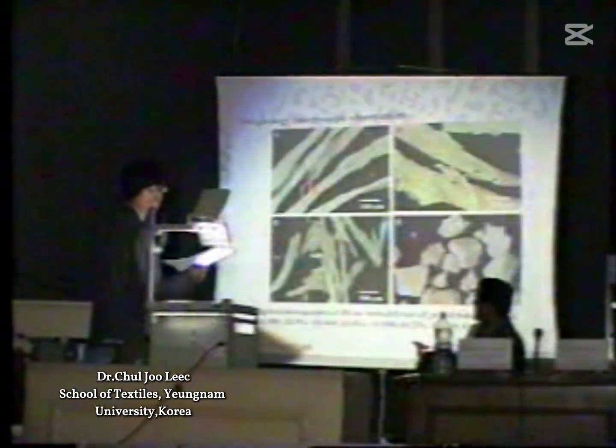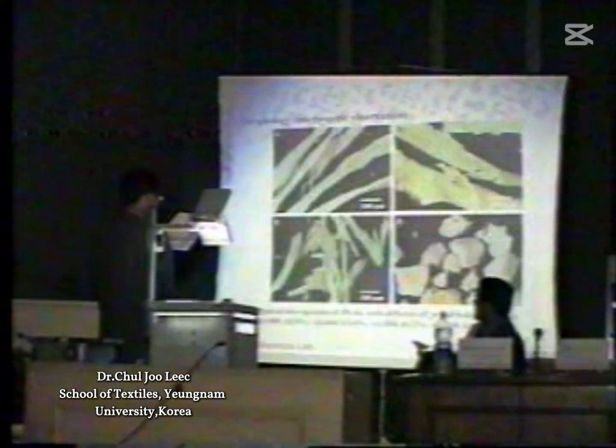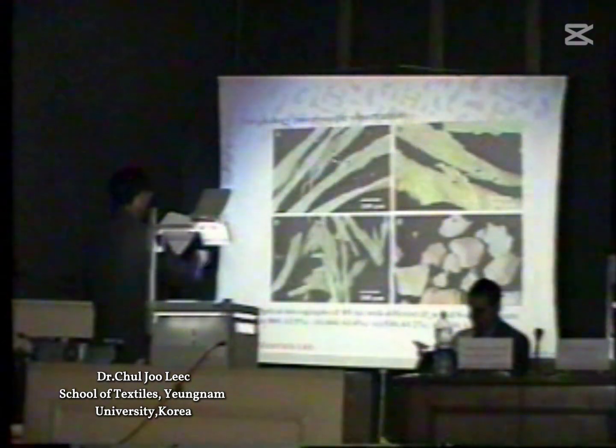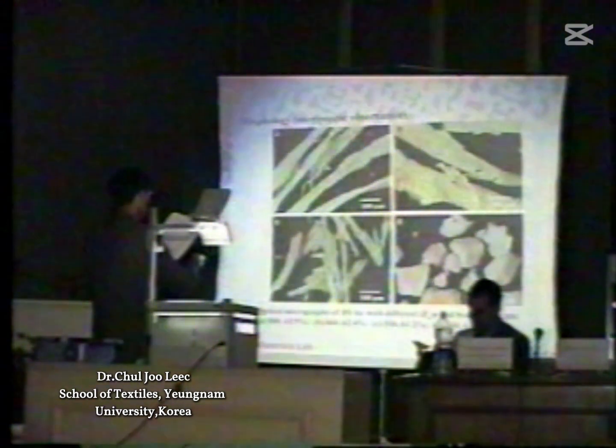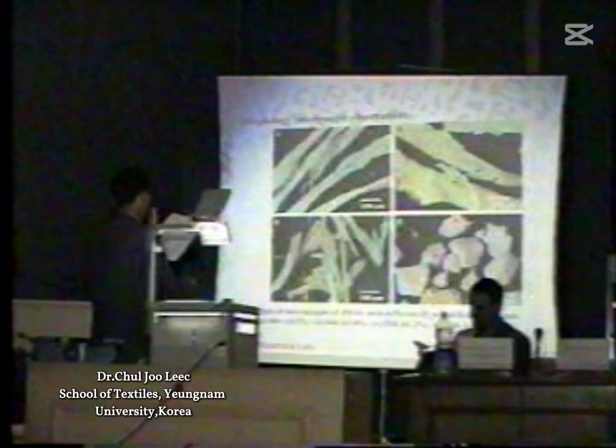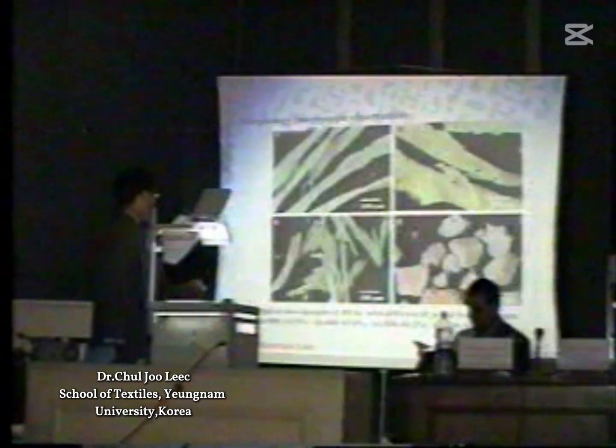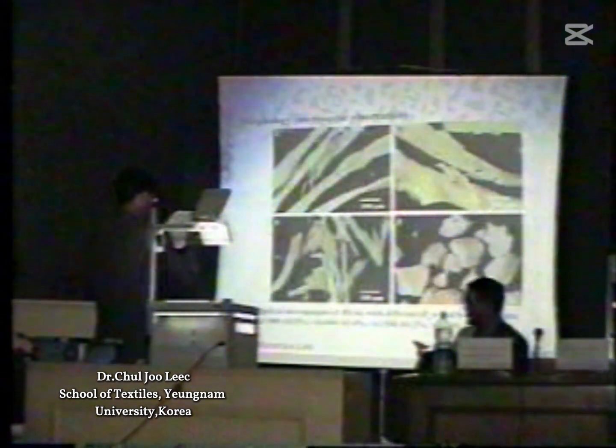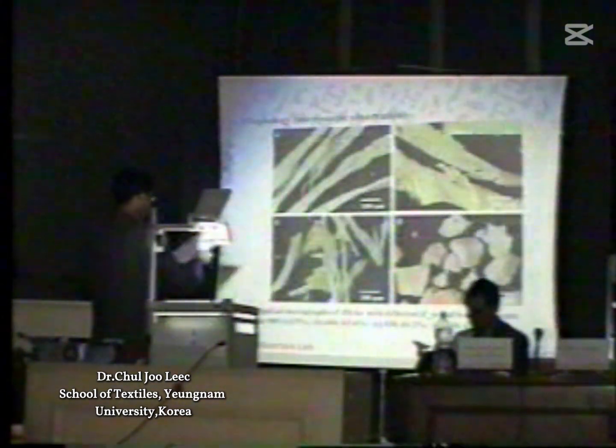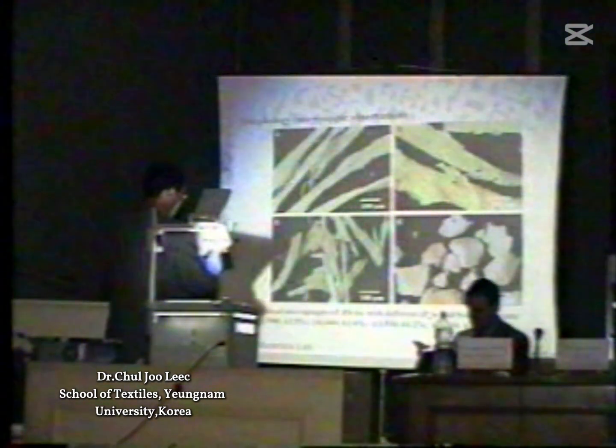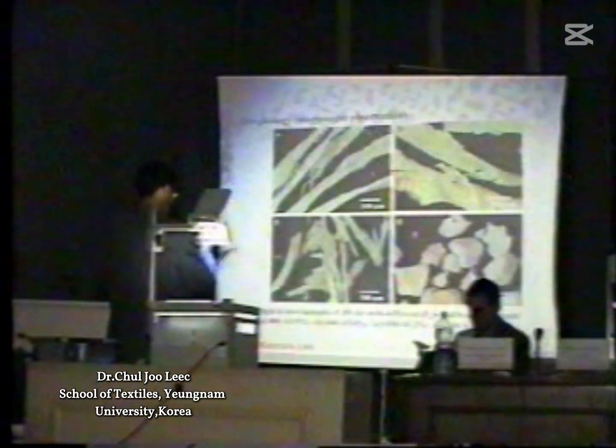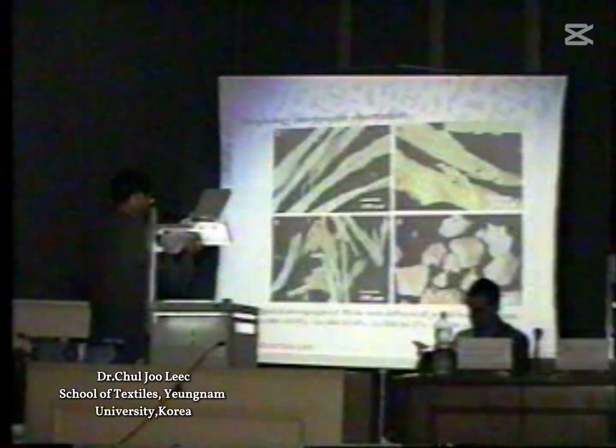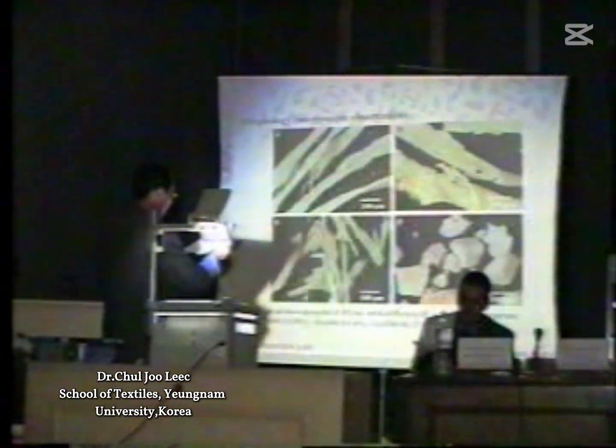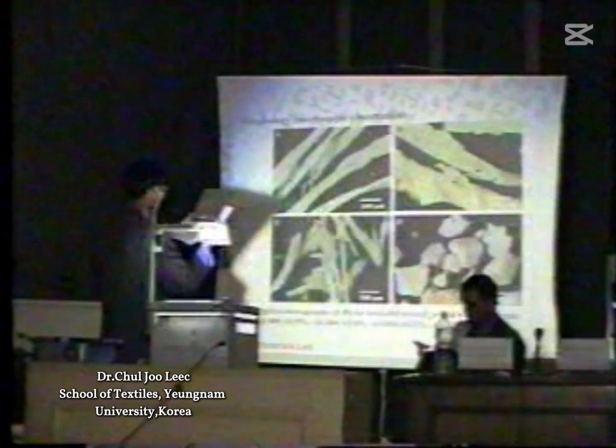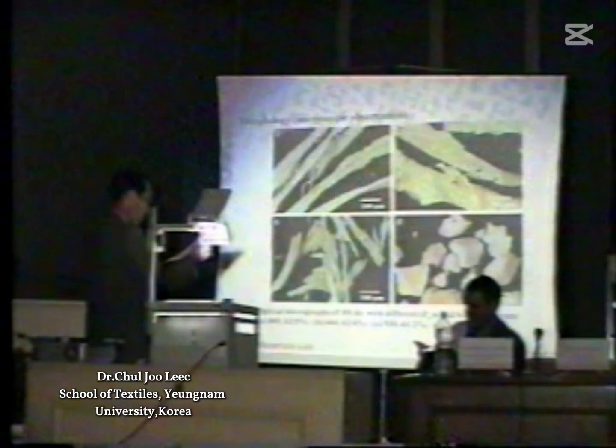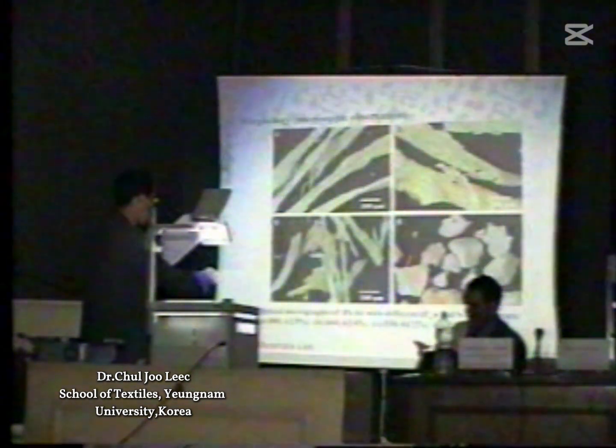This slide shows the molecular weight patterns of PVA. These four pictures have different molecular weights. The polymer in picture A has the highest molecular weight, and picture D has the lowest molecular weight. The degree of polymerization of figure A is 800, and figure D is 330. And the syndiotactic diad contents of all four polymers are over 60%. It's almost the same. As you see from these pictures, higher molecular weight polyvinyl alcohol has a microfibrillar structure in figure A, but the low molecular weight PVA is powder-like in figure D.